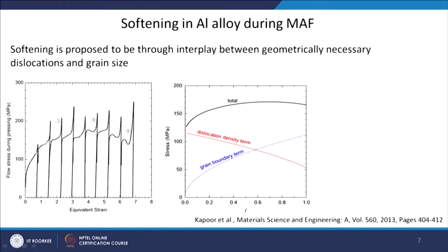So, you can see the effect of strain on the flow stress as you keep deforming. In the first cycle the flow stress is around 100 megapascal or so, which increased in the next cycle to around maybe 120 or 130 megapascal. Then continuously the flow stress is increasing, and then we are changing the path. Again it will go up and come down and so on. But as you can see, after 6 passes there is a decrease in the flow stress.